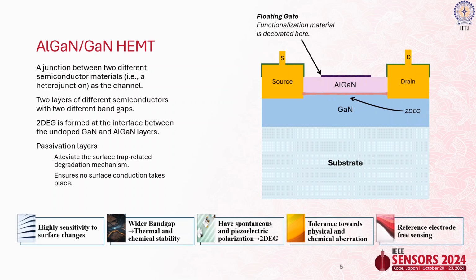As well as we are passivating all the surface except for the gate area so that we alleviate the surface trap-related degradation mechanism and ensure that there is no surface conduction taking place. Just like the ISFET, the principle that is working is due to the interaction of the functionalized layer and the gas. So it is based on a surface potential that is forming, that will lead to the detection.